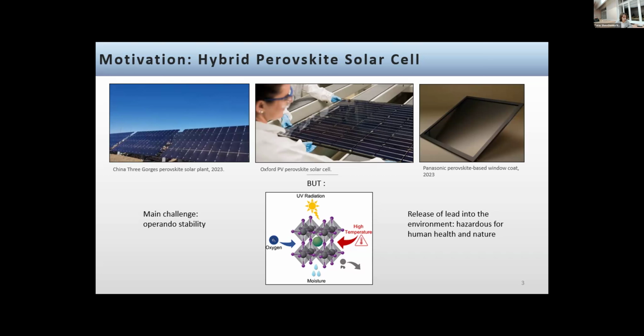However, not everything is so bright, because otherwise they would be everywhere by now. There are some significant challenges to the widespread adoption of perovskites. The most important is stability under actual operation conditions in the atmosphere. Hybrid perovskites tend to be chemically unstable when exposed to oxygen, moisture, and irradiation.